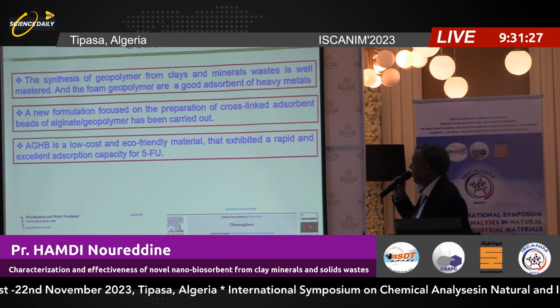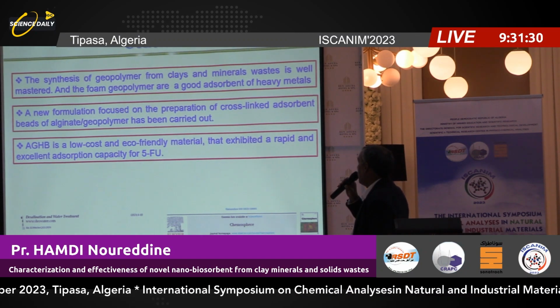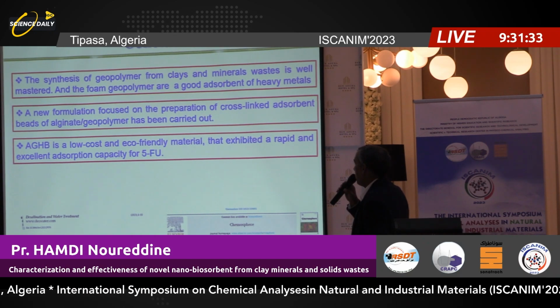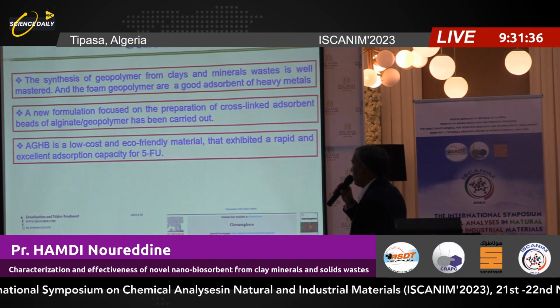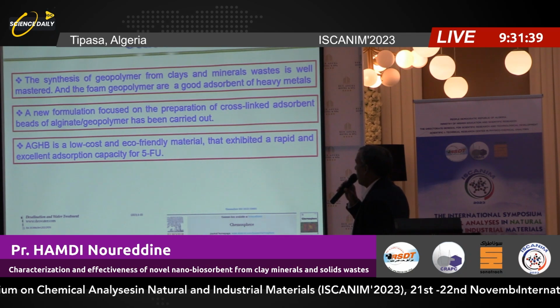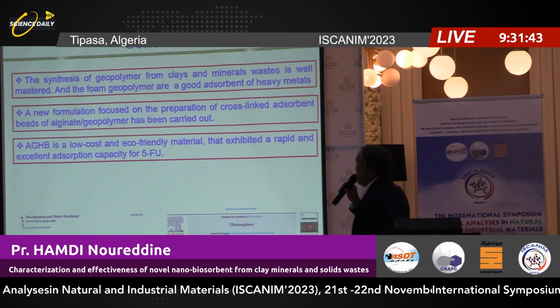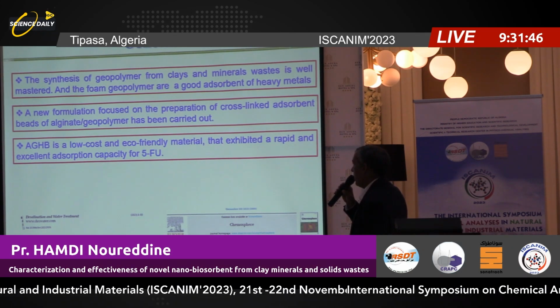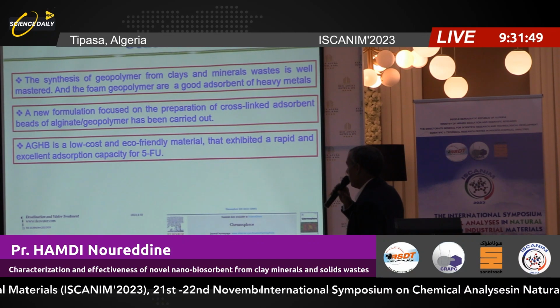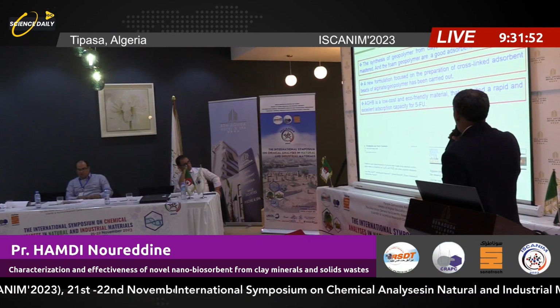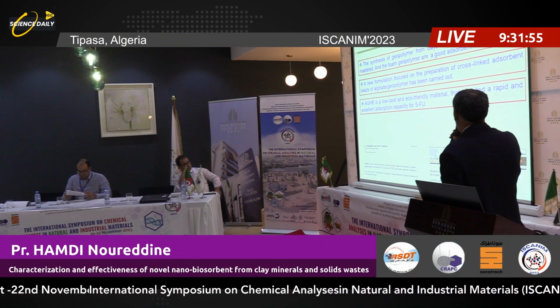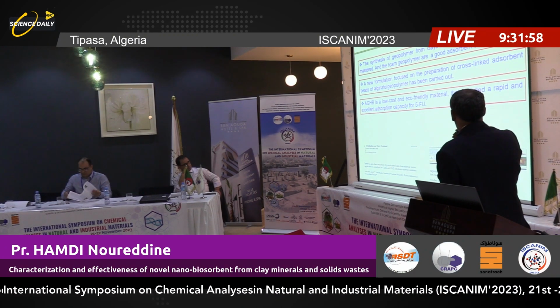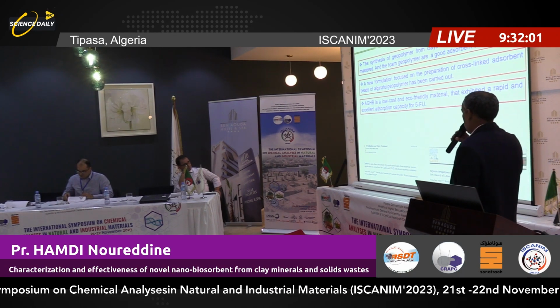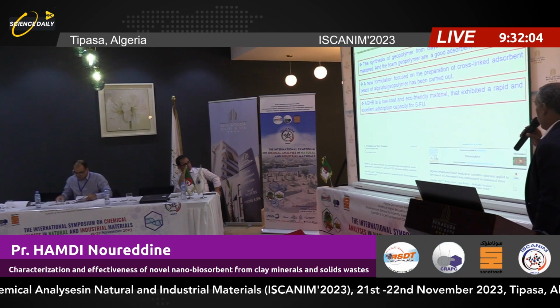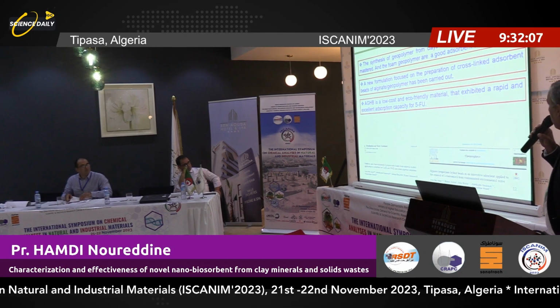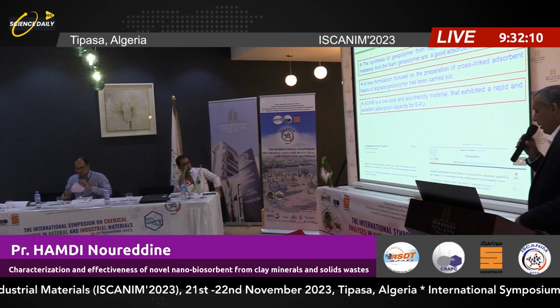As a conclusion of this part, the synthesis of geopolymer from clay mineral waste is well mastered, and the foam geopolymers are a good adsorbent of heavy metal. And the second conclusion is that a new formulation focused on the preparation of a cross-linked adsorbent, the alginate geopolymer, has been carried out, and the particles of the composite, with low cost and eco-friendly materials, exhibit rapid and excellent adsorption capacity of the 5-FU. This work has been published in Chemosphere.